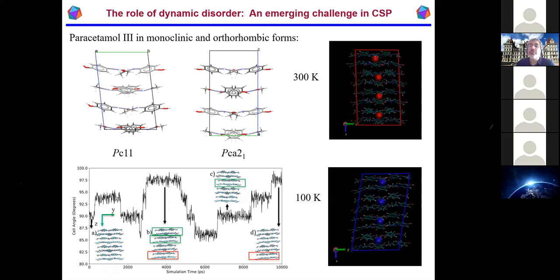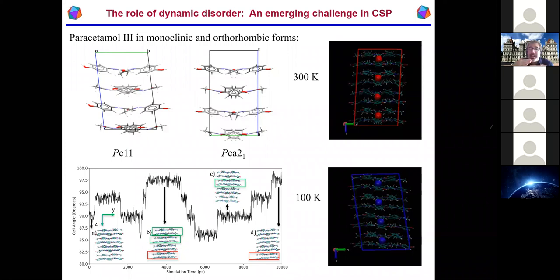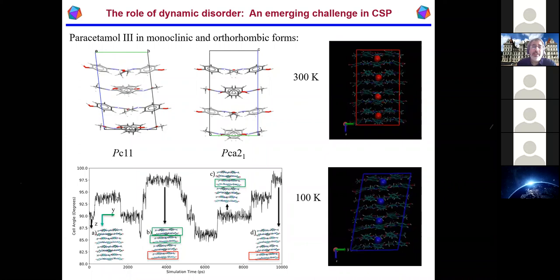And this is something that's never studied when people do crystal structure prediction. There are large segments of this 100 Kelvin trajectory you're seeing here where there's a very definite slippage of the layers. Okay, and that's actually creating a disorder within the structure. And that's something you'll never get from standard CSP. Now, of course, in order to sample at 100 Kelvin enough to get statistical relevance, you need enhanced sampling. And so this is using a temperature accelerated approach, all right, with the cell matrix as your collective variable. And you can see now very facile transitions between the orthorhombic and the monoclinic forms.